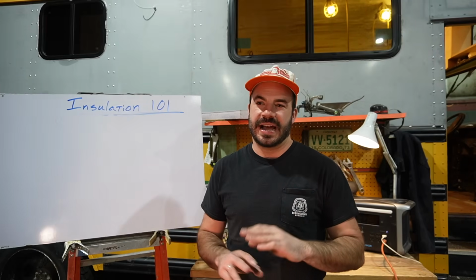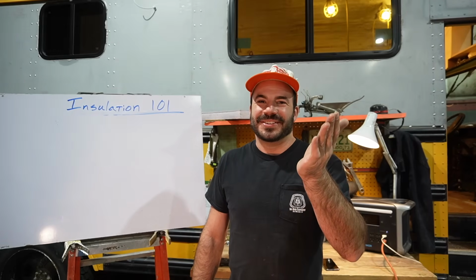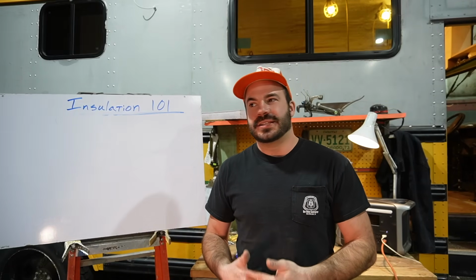Now that goes against everything I know, because the R value of aluminum and butyl rubber, which is what that is, don't buy into their marketing hype. It's nothing new, okay? They're saying it's proprietary and perhaps it is, but they even say on their site in the product description that it is still a butyl-based product. Well, the R value of those things together is going to be under 0.4 per inch of thickness. So there's just no way that we're going to see their claimed R value of 7 out of just 1/8 of an inch of thickness.